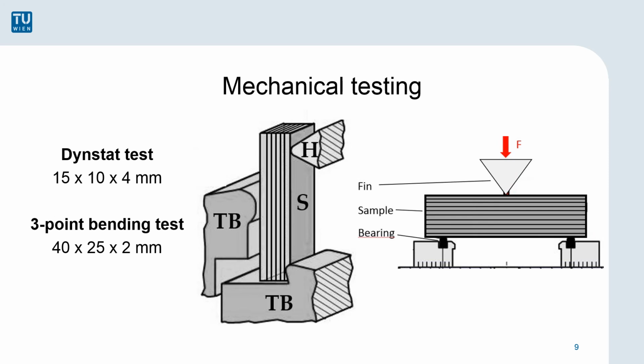The samples, displayed with S, are placed in the machine and fixed between the two thrust blocks TB. A hammer H swings downwards and punches through the sample. The absorbed energy of the samples can be deduced from the height of the hammer reached after punching through the sample. This energy is equivalent to the fracture toughness of the sample. The direction of the force is perpendicular to the interfaces of the layers. This testing setup ensures that the crack has to propagate through all layers of the specimen.